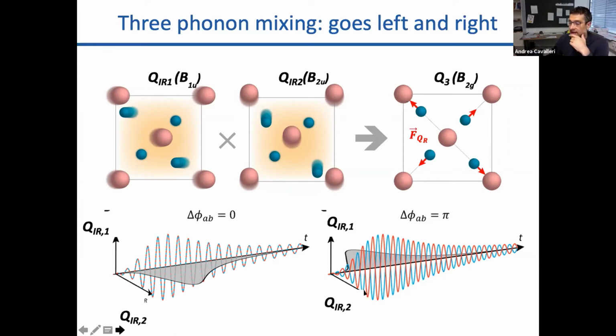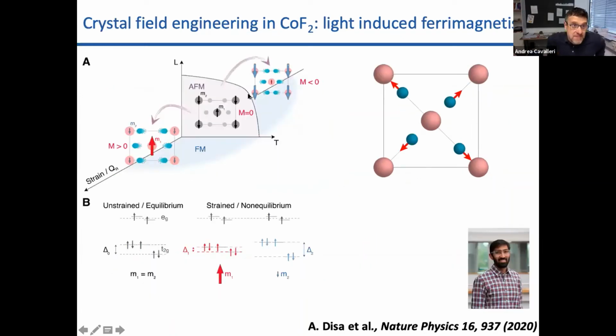And so this comes with a proposal which we then experimentally proved to be correct, which we applied in a well-known piezomagnetic material, cobalt fluoride, which is an antiferromagnet, which when it's strained in either the compressive direction or the tensile direction, can unbalance the crystal field environment around these two spins of the antiferromagnetic pattern and make it inequivalent, making the material a ferrimagnet, or effectively a material with a ferromagnetic moment. So what's very nice about this is that one, you can now do this in two directions with a laser pulse, exactly as Paolo had predicted in his paper.